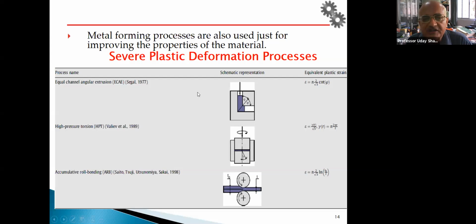So this one is equal channel angular extrusion. Here what I am doing is an extrusion process only. I just took a billet and passed it through a die. This die angle is 90 degrees, so there is a 90 degree shear angle, and after that I will repeat the process many times. So I will get a lot of strain. It will cause severe plastic deformation. The ultimate shape remains the same. Then high pressure torsion: I will have a small disc of raw material, and this is one anvil which is stationary, the other anvil is rotating, but at the same time it is putting pressure. So I am putting the pressure and torsion together, and due to that severe plastic deformation is created, and its microstructure gets changed.